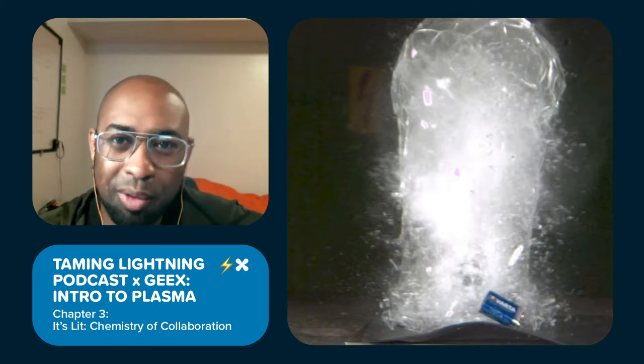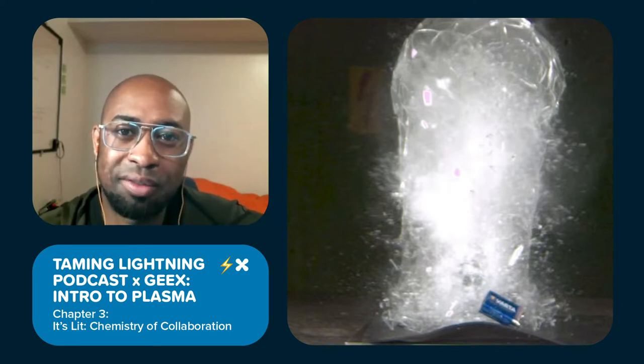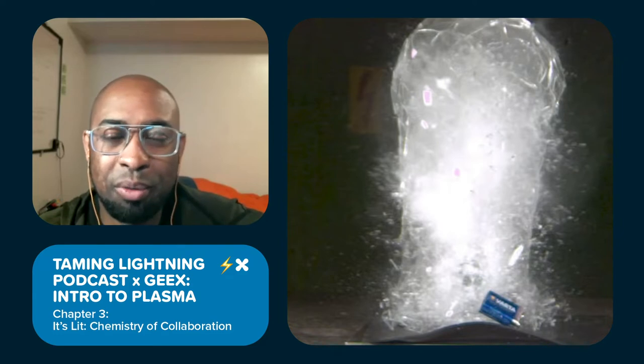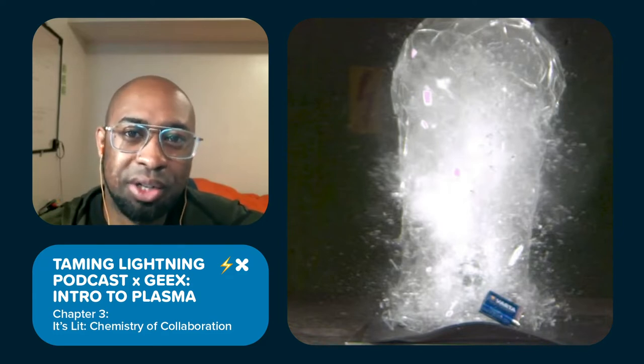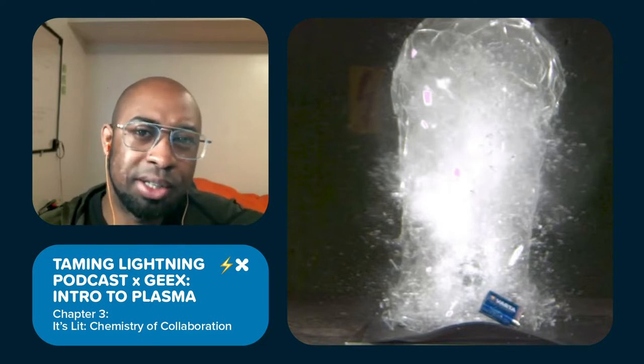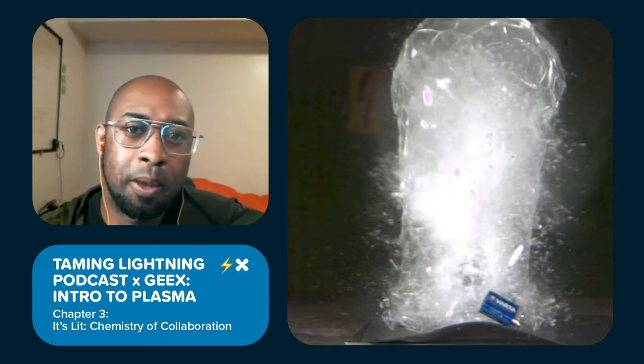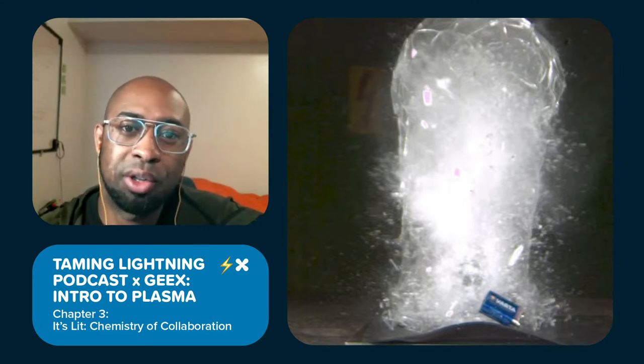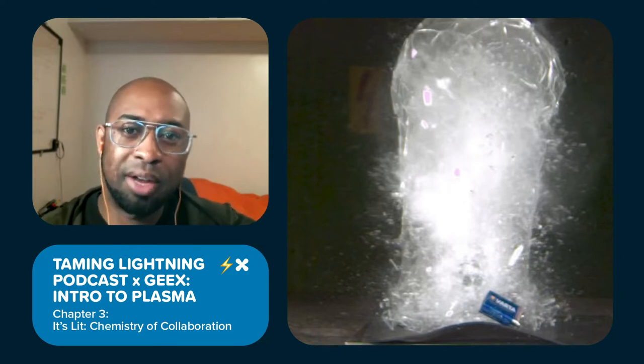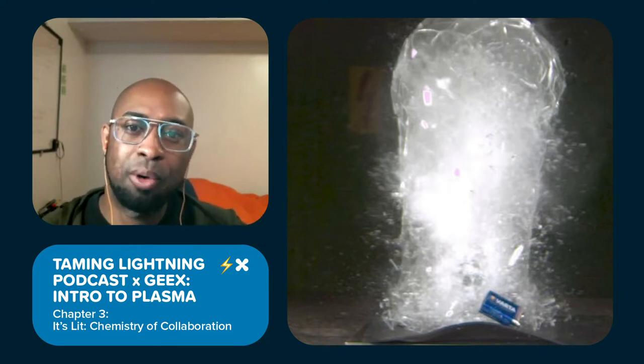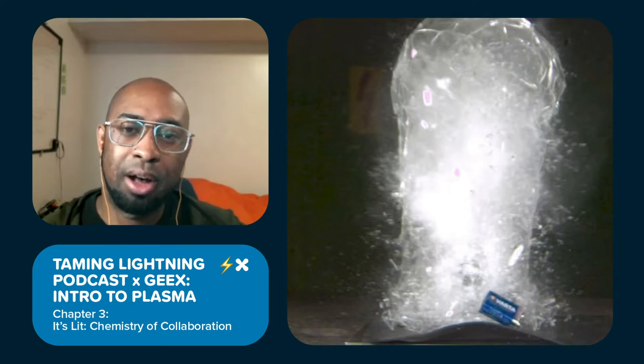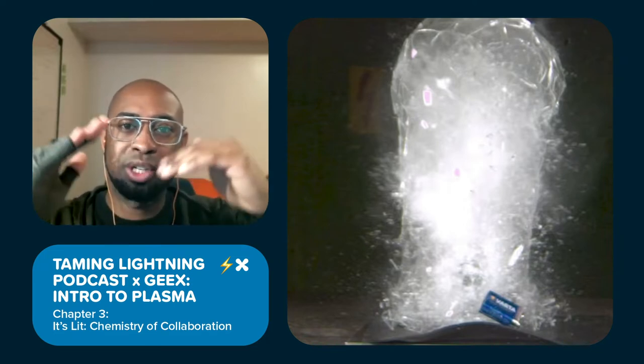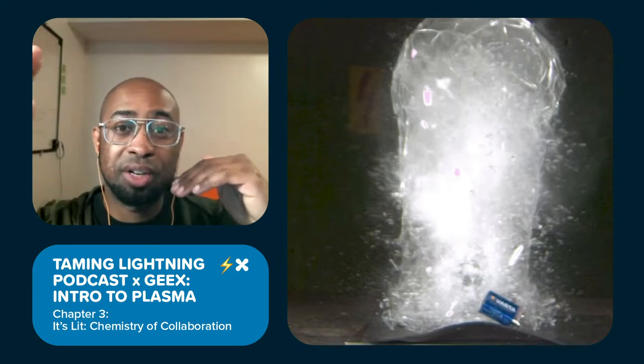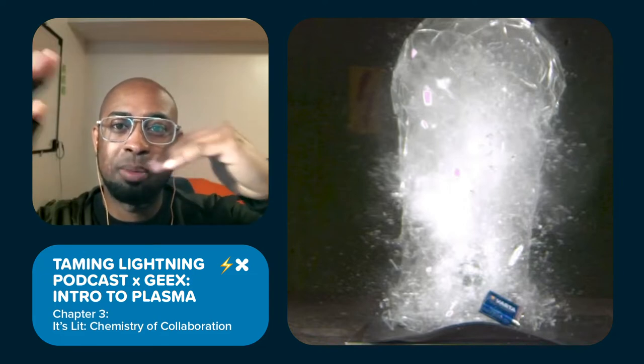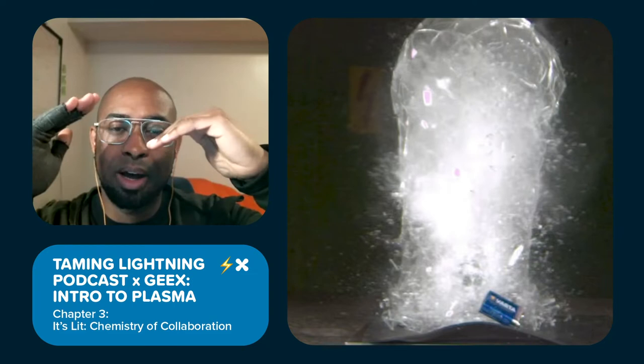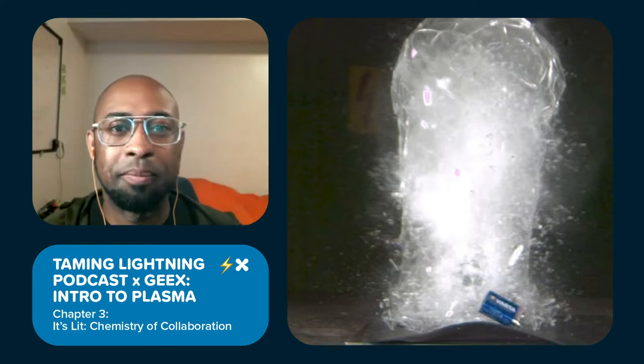This will also be the same area where you get your nice behaviors and effects and arcs, so many people will find themselves past this range already. Now this works because you have less pressure to displace. You know, air will flow from a high pressure to a lower pressure area. So the bigger the vessel, the more area is displaced, therefore the more power the displacement becomes. If you change the differential between atmosphere, which is 760 torr, and you close that gap a little bit more, the less force is produced by that.